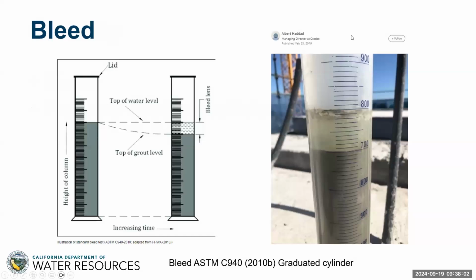Right, so one of them is what we call bleed. Basically we take a sample of the fluid grout, watch it over a period of maybe 2 or 3 hours until it fully hydrates, and we measure progressively the amount of water that is decanted to the top of that measuring cylinder. This decantation occurs simply by the settlement of the individual particles. Now, bleed is not a good thing, because unless it can escape into the ground, into the formation, it will remain in place either as, if you like, little balloons of water or vertical ribbons. In either case, it has the potential to allow water to move through the system. Next slide.